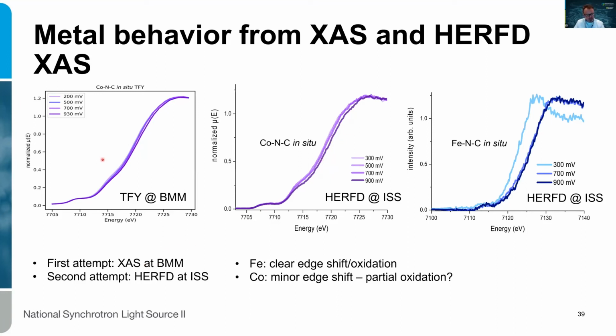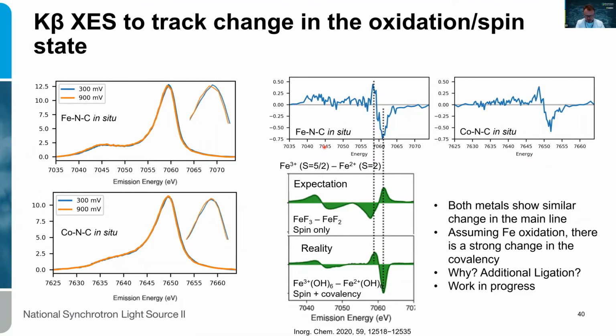And again, by comparing the regular fluorescence data with the HERFD, we see better resolved changes in the cobalt edge that correspond to the oxidation during the electrochemical process that we were interested in. Those are the two different materials, the cobalt and the iron. In the case of iron, the shift at higher potential is considerably larger, which is what we're trying to understand in terms of the reactivity of those materials. I'm going to skip this slide probably.